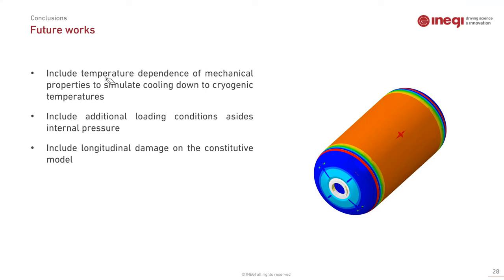I only have another question because I'm planning to go deep into this at some point. Okay. It is clear that the Young's modulus can be affected by the temperature, but how does temperature affect the strength of the material, like the yield stress? Or do you have any evidence of how it evolves? It decreases too, I suppose, with the increase of temperature, for example. How will the yield stress change with temperature? Yeah. Okay. For hot temperatures, I have never tested the material, for example, at 80 degrees. But for lower temperatures, the material tends to be more brittle. Let's say the yielding and the failure stress become more similar.